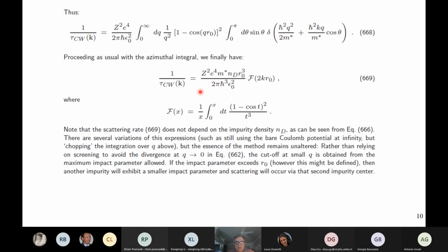The fact that there are these two models, you can criticize some of the approximations that have been made, you will be justified, and indeed lots of people have done so. The agreement between the mobility calculated using either of these methods sometimes works, and in some situations doesn't quite work. In some materials it may work well over a wide range of density, in other materials or different types of situations, not. For example, in high electron mobility transistors, when you have what's called delta doping, you dope the barrier material, and the electrons that spill over give you the electron density in the channel. So scattering is now between the electrons and centers which are removed from the channel themselves. Neither of these methods worked terribly well.